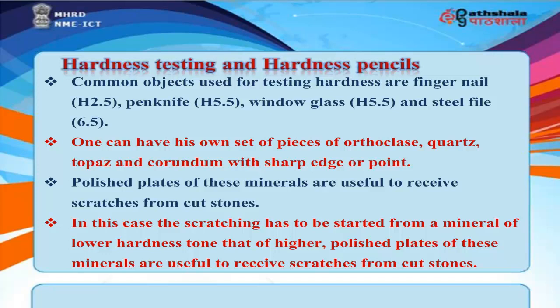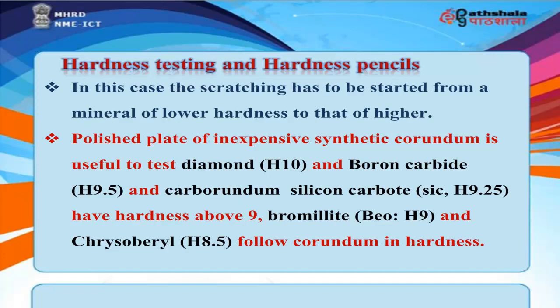One can have his own set of pieces of orthoclase, quartz, topaz, and corundum with sharp edge or point. Polished plates of these minerals are useful to receive scratches from cut stones. In this case, the scratching has to be started from a mineral of lower hardness to that of higher. Polished plates of inexpensive synthetic corundum are useful to test diamond H10, and boron carbide H9.5 and carborundum SiC, silicon carbide H9.25 have hardness above 9. Bromellite BeO H9 and chrysoberyl H8.5 follow corundum in hardness.